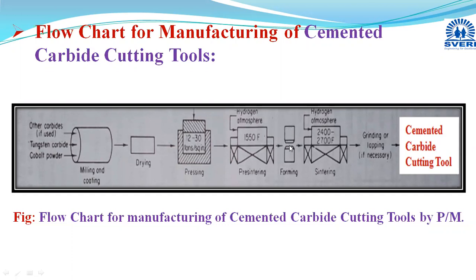When the sizing operation is done, it is given to the final sintering at the high temperature zone of 1350 to 1550 degrees Celsius, where the cobalt metal melts and it cements or binds the tungsten carbide or molybdenum carbide particles. During this sintering, diffusion, densification, recrystallization, and grain growth occur. Then it is given to the machining operation, which is done in two ways: rough and fine machining. Then the cemented carbide cutting tool is obtained, which is tested and inspected for its properties, shape, size, and whether any kind of defect is present or not.